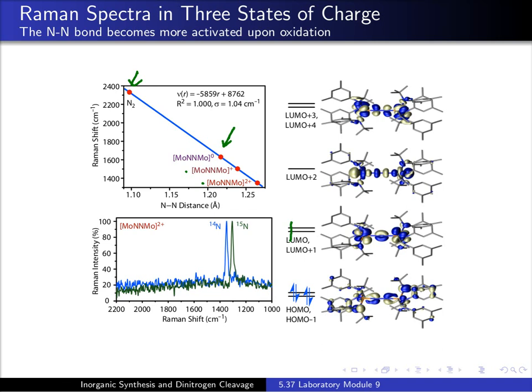In the purple neutral species, this degenerate orbital has two electrons in it. It is actually an orbital in the pi system that spans the tetraatomic MoNNMo core in the system, and it has NN bonding character. So the effect of oxidizing first by one electron to make the monocation, and then by another electron to make the dication, is actually to increase the NN bond length. Those have also been characterized by X-ray diffraction studies, so we know the NN bond length, and it gets longer as you take out first one and then a second of these unpaired electrons.